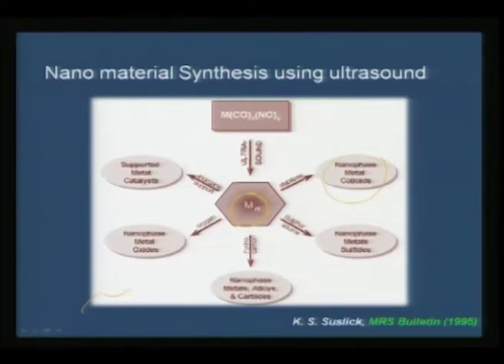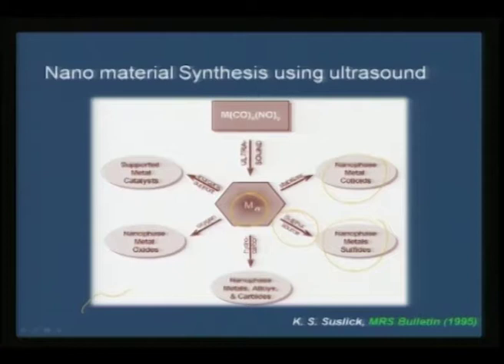where you can essentially stabilize these nanoparticles in a suspended form. Or if you are going to bubble this with some sulfur source, either elemental sulfur or sodium sulphide or some other sulfur source, you can essentially get nanometal sulfides. For example, if you take cobalt and you bubble it with sulfur, in the presence of ultrasound you will get cobalt sulphide. If you take any hydrocarbon and try to trap this, then you can get nanophase alloys or carbides. If you are going to use this in ambient condition, that is in the absence of any inert atmosphere like argon or nitrogen, in the presence of oxygen you can directly convert that into any metal oxides.